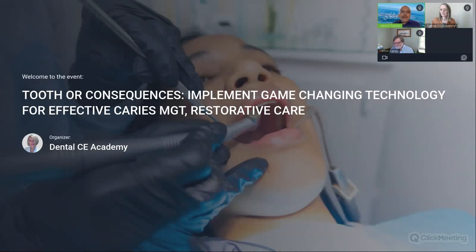Because if the composite, again, we think that when we put a composite into the mouth, that it is fully polymerized. Well, at best, maybe it's 65% completely converted. There's still a lot of unfilled resin floating around in there. And so that's where a lot of cytotoxic studies have been done and shown. So what Kuman's referring to and what Cliff has been talking about is that our materials are problematic, and if we don't use them properly, it's going to create an issue.